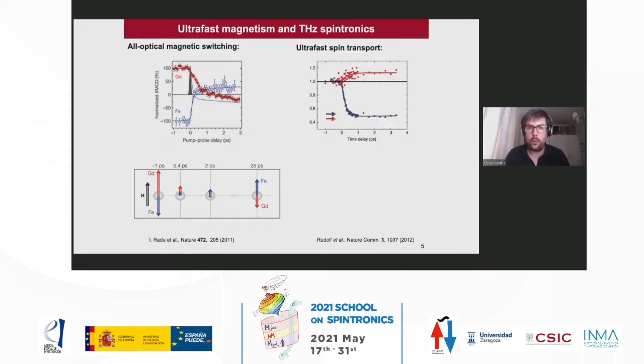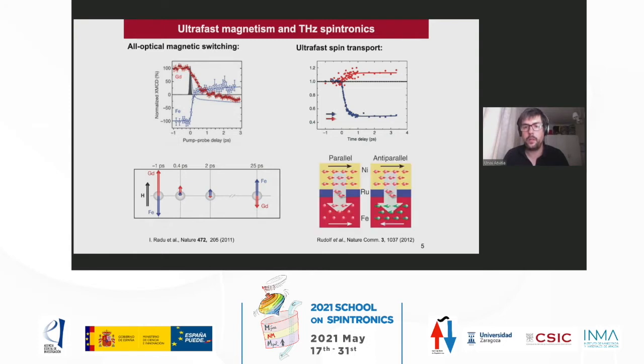It's also already possible to create ultrafast spin currents. This can be achieved in bilayers, for example of nickel and iron, where applying a femtosecond laser pulse to nickel creates an ultrafast spin current that is injected into the iron layer, and the iron layer increases its magnetization when they are parallelly aligned.